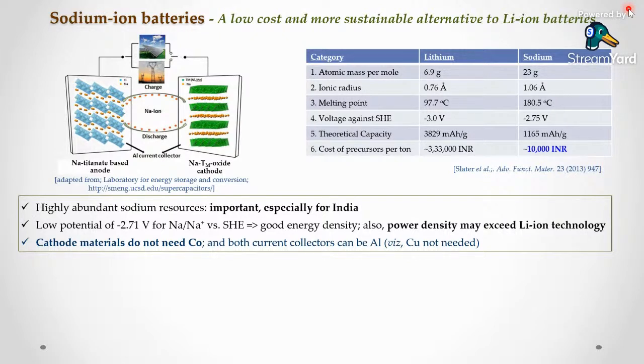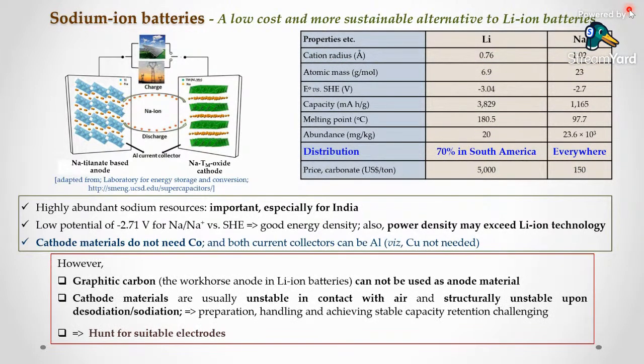The third advantage is that the cathode materials can work very well. They can be very stable in terms of the structure and the electrochemical performance without the need of cobalt as one of the transition ions. There are obviously a lot of problems, and especially given that sodium-ion battery is still an emerging system, one of the major problems is that graphitic carbon does not work as anode material because sodium ions do not get intercalated into the graphitic carbon lattice, unlike the lithium-ion counterpart.